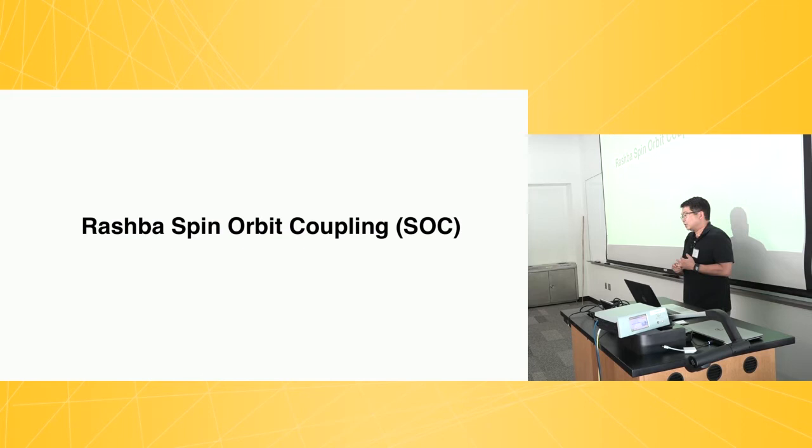But the thing that you lose is, for some processes you care about spin current, which is polarization times the current, right? As you make it more and more resistive, you start reducing the spin current. That's different than the spin injection efficiency. So there's a trade-off, and if you want to balance those off, somewhere in the middle is ideal. There's an optimal point. How thick it should be? It varies. The optimal point is where you'd want the barrier resistance to match the resistivity of the channel or the spin resistance of the channel. So there's some maximal point there.